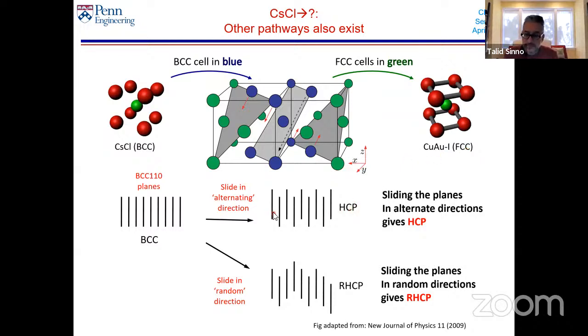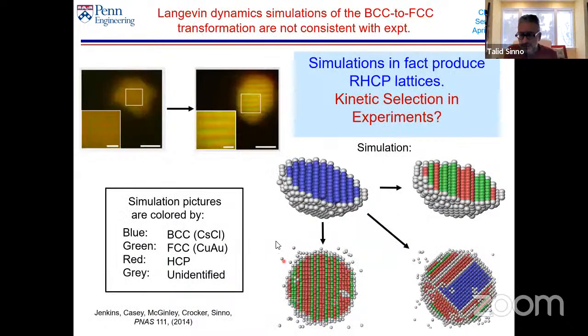And so that says that as I slide planes up and down, I can either form HCP, I can form FCC, or if I mix the two, I can form random HCP. Okay, and all of these have the same energies. So we started doing some simulations and watching crystallites undergo these transformations. And what we saw was, as you would expect from a simple statistical analysis, that you would see both HCP and FCC in a random way. The color here, red is HCP, green is FCC, and indeed they're random. So whenever you start out with BCC, you cut the crystal in half just to view it, and you'll sometimes see transformation starting in this direction, then in this direction, and then they meet here and the crystal gets locked and it can't finish.